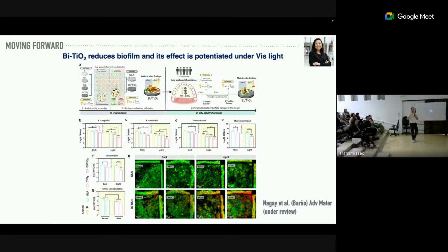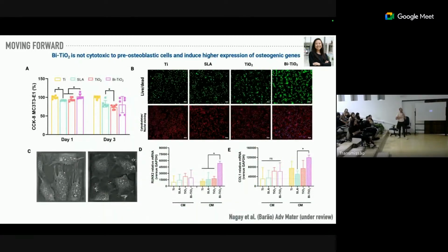We normally use 3 or 7. And then we apply the light at the end, and even in the in situ model that tried to resemble this composition, we also observed a good effect. We also tested a recolonization of this surface after light exposure, and the recolonization was not higher. So you might have no alteration on the surface that might promote greater bacterial attachment again.